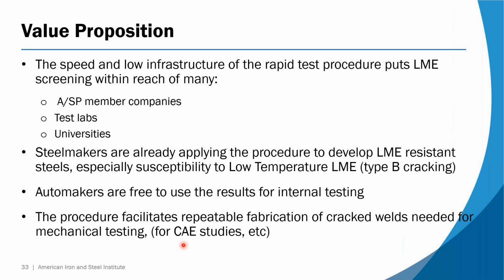Anybody's free to use the results for internal testing. And we weren't intending this, but because it's pretty repeatable at making cracks, the people that are studying LME cracks for mechanical testing, fatigue, CAE studies, etc., are starting to use this method because it gives you a way to control the crack depth more accurately.